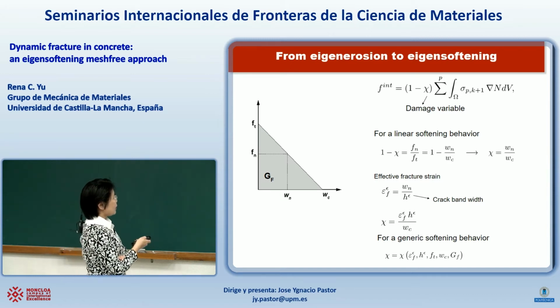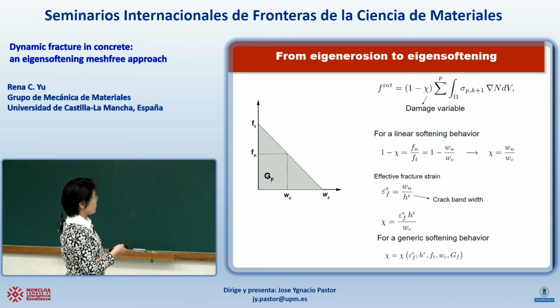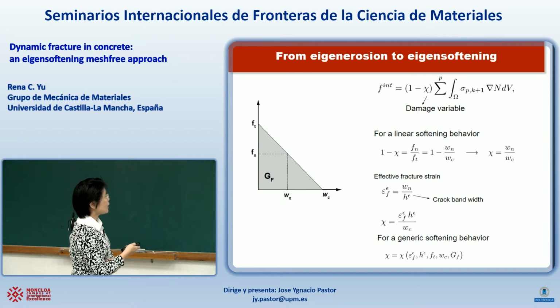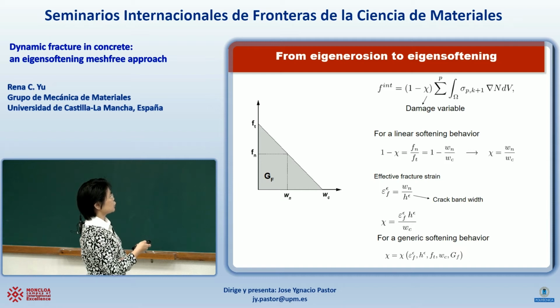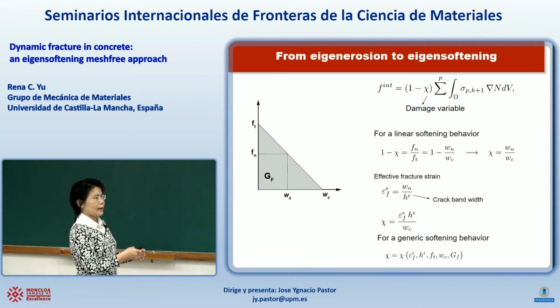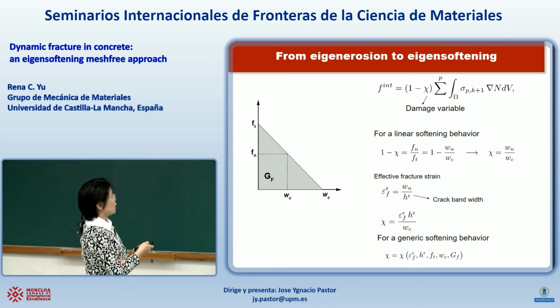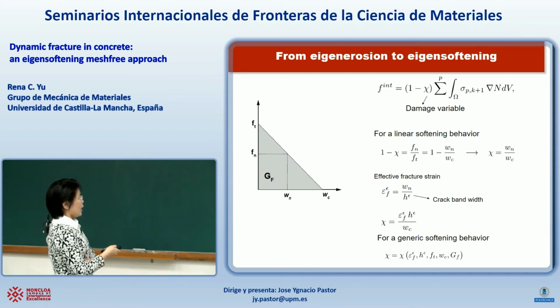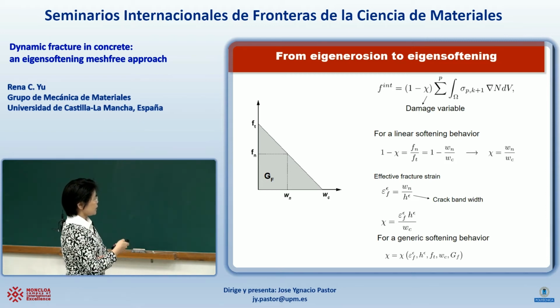So we define a damage variable, for example, corresponding to an opening Wn. This corresponds to a softened stress, which is Fn. We define a damage variable so that when we calculate the internal stress, this damage variable makes the material less stiff. So when this is equal to 0, we have our perfect material. Then this is the same as before. If it comes to this point, it will be 1, and then the material has lost all its resistance. And if we have a specific linear softening behavior, the damage variable can be calculated directly as this opening Wn divided by the critical opening Wc.